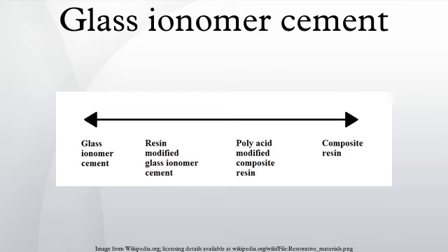For core build-up, some dentists favor glass ionomer cements for cores, in view of the apparent ease of placement, adhesion, fluoride release, and matched coefficient of thermal expansion. Silver-containing GICs or the miracle mix of GIC and unreacted amalgam alloy have been especially popular. Some believe the silver within the material enhances its physical and mechanical properties. However, in vitro studies are equivocal, and a study of a cermet used to fill deciduous teeth showed that it performed less well than a conventional GIC.